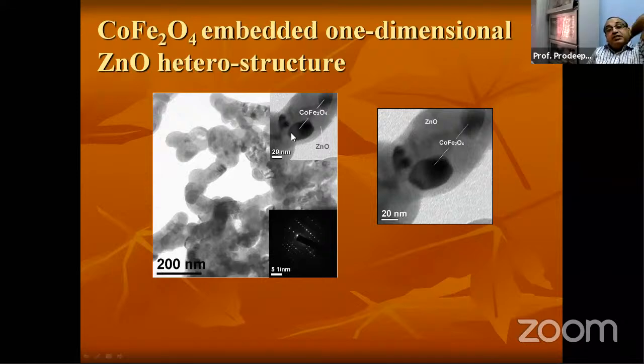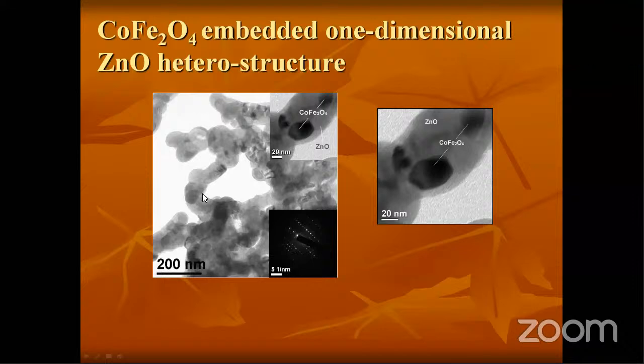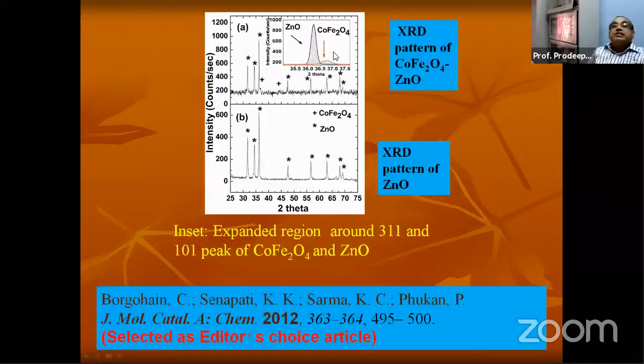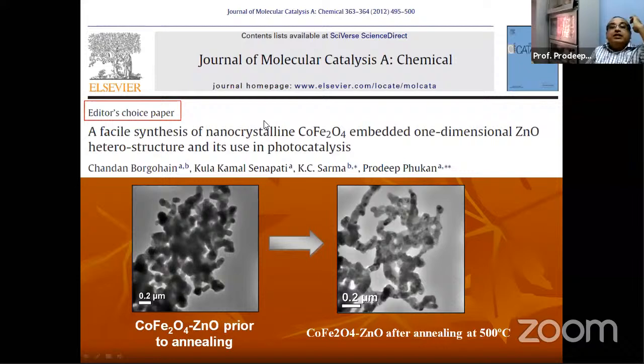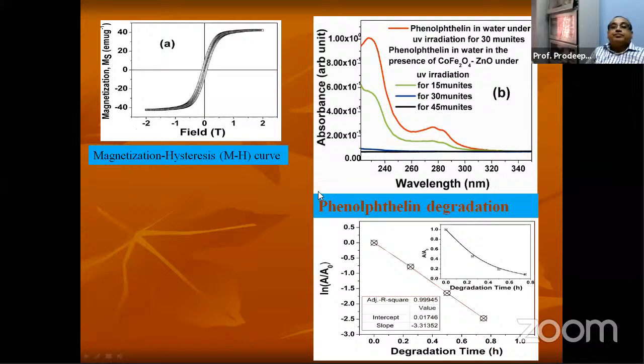Interestingly, during the synthesis, we found such kind of growth. And this is the XRD pattern, and finally this was used for degradation, as a photocatalyst. And you can see here, this is prior to annealing, after annealing, so the structure changes. So this is phenolphthalein degradation we have studied. We got this kind of property.